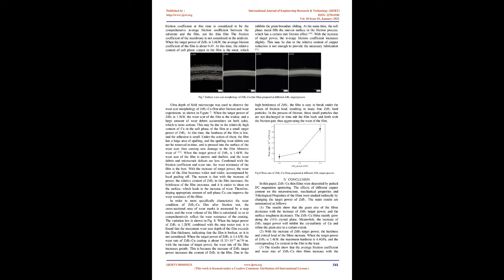This is mainly due to the high target power, which improves the activity and diffusion ability of the deposited ions, and makes the structure of the film-substrate interface become compact. 3.5 Tribological Properties. Figure 6 shows the friction coefficient of ZrB2-Cu films prepared under different sputtering power of ZrB2 target.